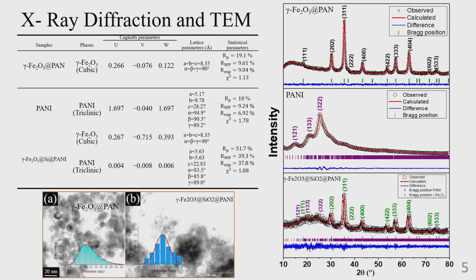The imaging microscopy revealed the real nanoscopic size of both magnetic polymer samples, as it can be noticed here. Core single shell nanoparticles exhibit a mean particle size of 11.6 nanometers, confirming that the co-precipitation method allows the formation of nanoparticles with small grain size. On the other hand, the core double shell sample in this figure reveals improved nanoparticle dispersion, increasing their colloidal stability and avoiding agglomeration. From this, one can expect that the interparticle magnetic interaction also becomes reduced.